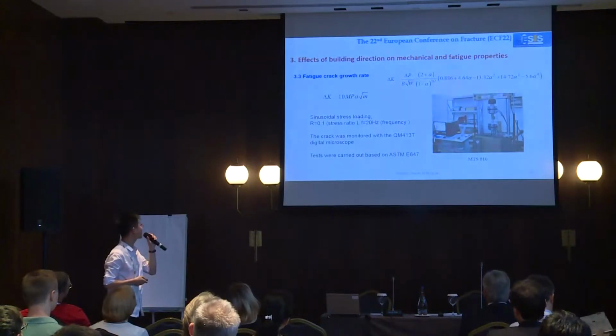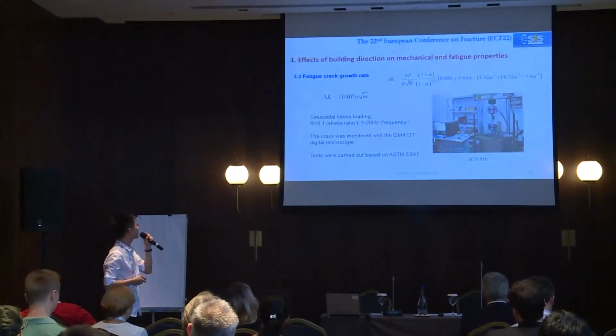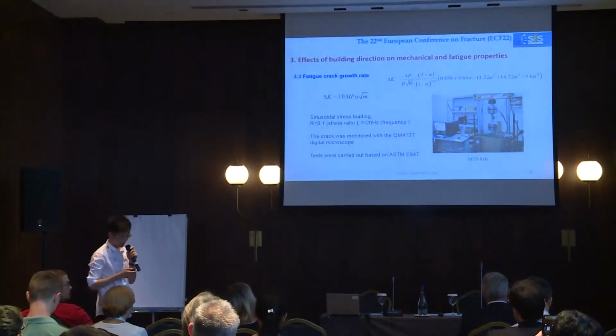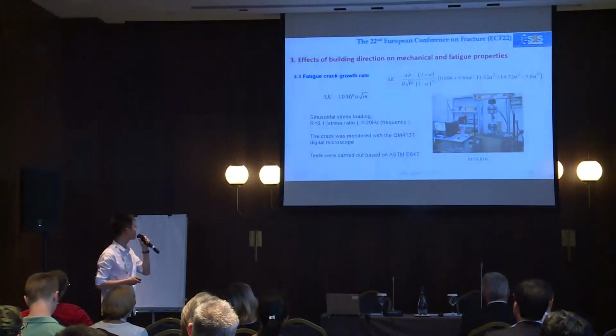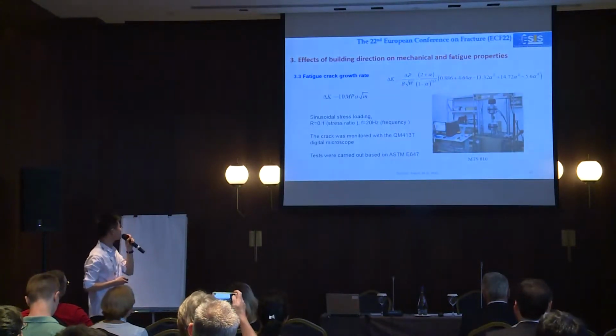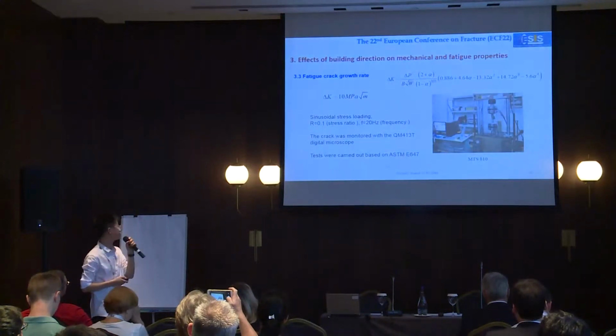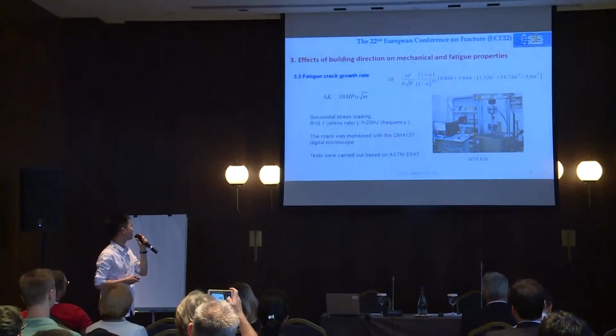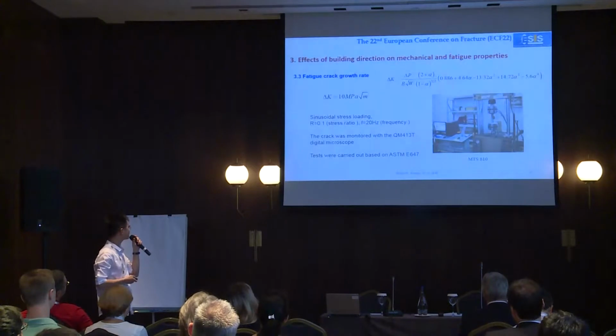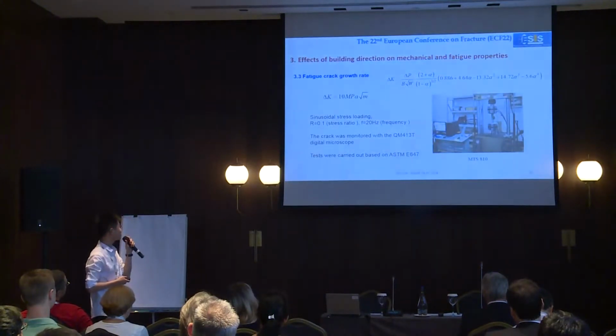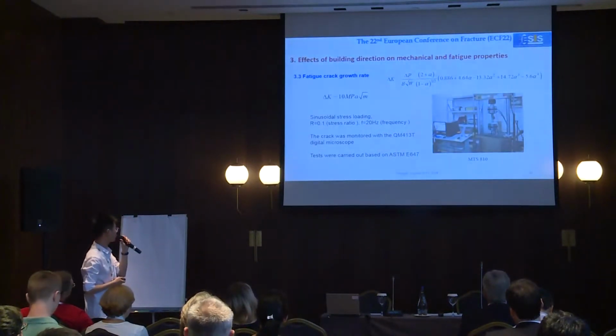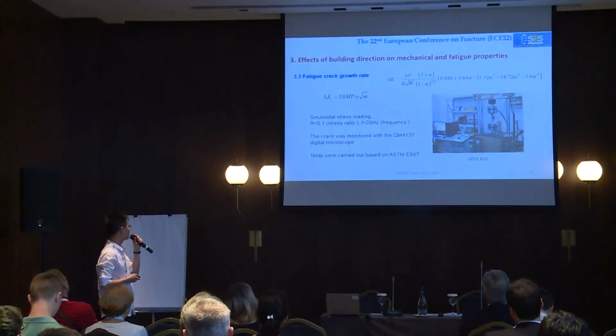Last, we studied the effect of building direction on FCGR. In our test, delta K equals 10, and since stress loading is adopted, stress ratio R equals 0.1, and frequency equals 20. The crack was monitored with a digital microscope, and the tests were carried out based on ASTM E647.